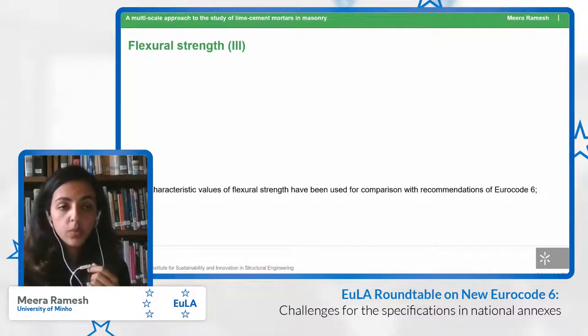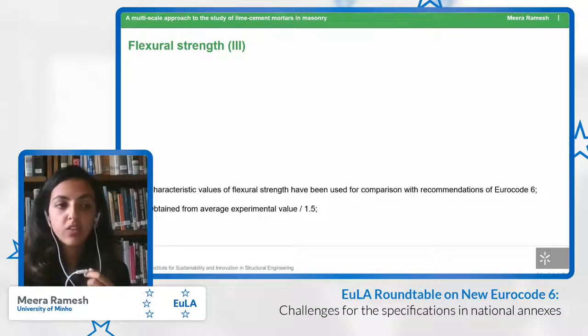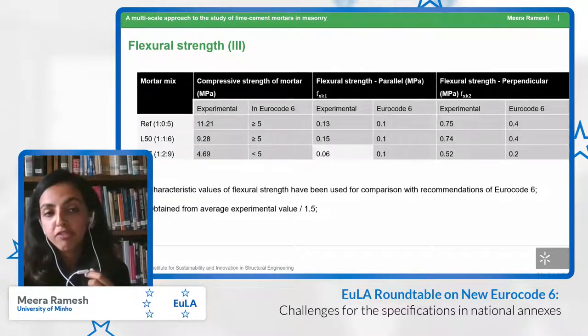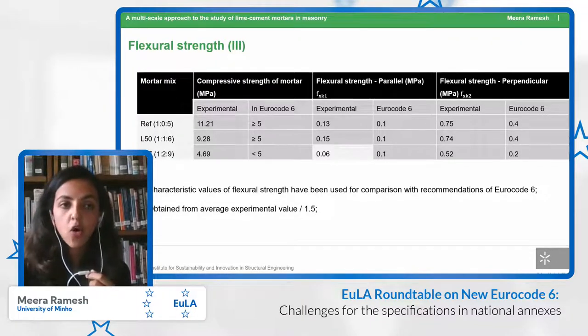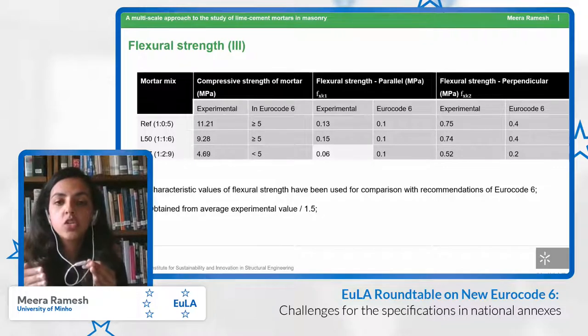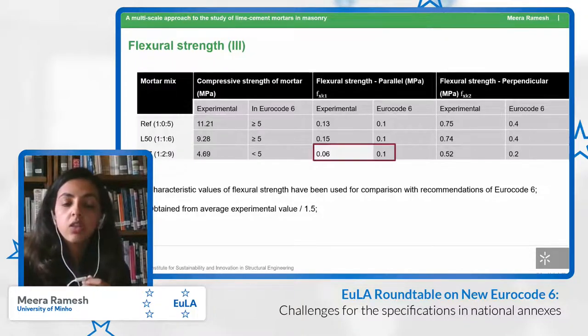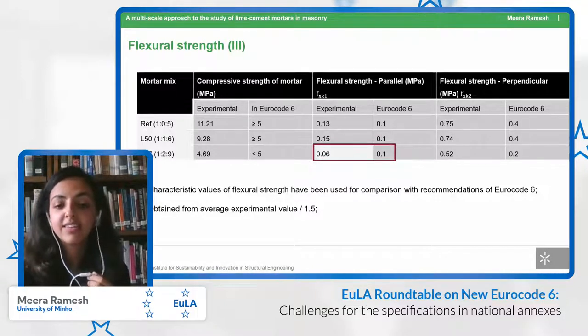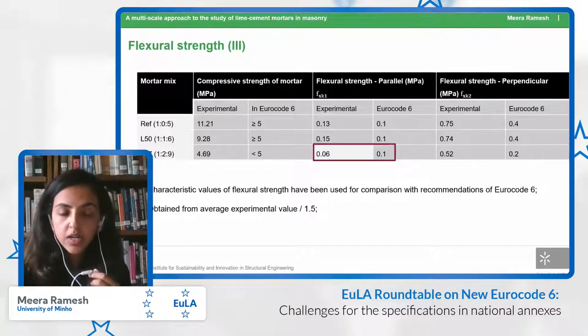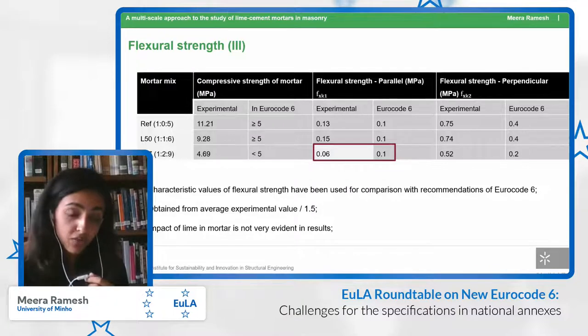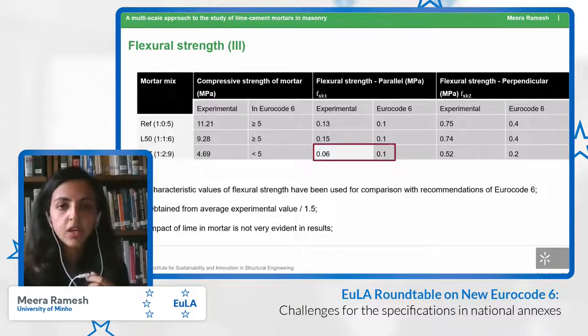To compare this again with the recommendations of Eurocode 6, we had to convert the average experimental values into characteristic values, and this was done by dividing them by a factor of 1.5. The important thing here is that all the values that we obtained were higher than the recommendations of Eurocode 6, which is good because this means that the estimation of Eurocode 6 is on the safer side. The only one that was not on the safer side was flexural strength in the parallel direction for the mix L67. The other important thing here is that unlike in compressive strength, the impact of lime did not show a very clear pattern. What seemed to play a greater role was the compressive strength of the mortar itself.